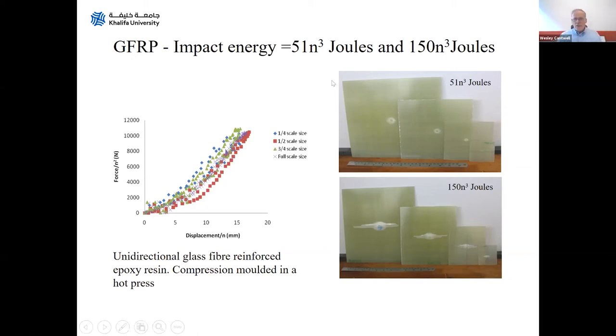If you look at the damage then, this is after 51 N cubed joules, starting with the largest really, because the damage is clearer to see there. You can see this circular delaminated area here in the middle, quite clear. Again, you can see such damage in the three quarters and the half. And again, with a bit of poetic license, I think you can see some damage there in the quarter scale as well.